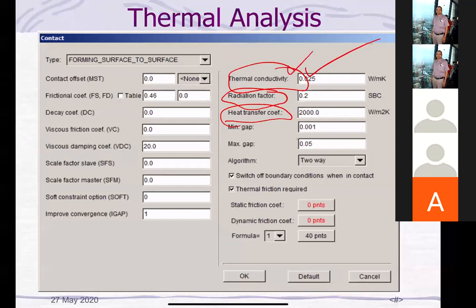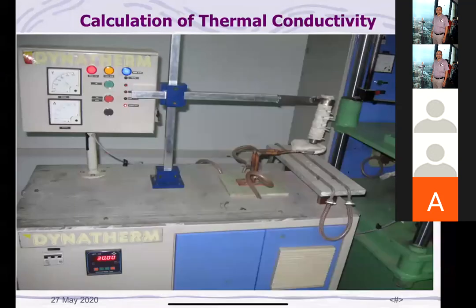So this is my heater, and the punch material is here, and over that, this is called insulation. And if you can see now, here there are tubings coming out, correct? Here I am measuring the temperature. So once the temperature is stabilized, here I have fixed it at, say, 400 degrees centigrade, and this portion is at room temperature. Once the temperature stabilizes, I can measure this temperature T1, T2, T3, T4, like that. By that, I can calculate all the thermal parameters.